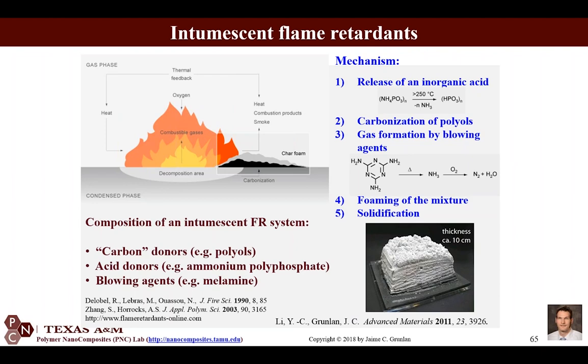So, of course, we would like fires to be stopped. And so there's this intumescent concept, and a lot of skyscrapers, the steel beams in a skyscraper have this intumescent kind of white, thick coating on the steel beams. And when there's a fire, it puffs out, and you can see a thickness of 10 centimeters down in this corner picture. That's on a piece of steel. We wanted to do the nano/micro version of this using layer by layer assembly.